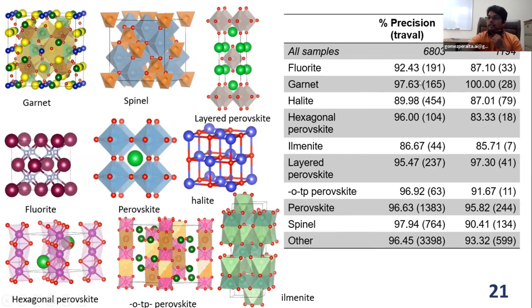In the table, you can find the results after training, validation, that is optimizing the artificial neural network, and in the test set, which are compounds completely different than those used in the optimization process. The average precision for the compounds in the test set was 91%. And the lower precisions that you can find in the table are ascribed to a scarce number of compounds having the structures. For example, there are only 7 compounds in the test set with the ilmenite structure and 18 compounds with the hexagonal perovskite structure.